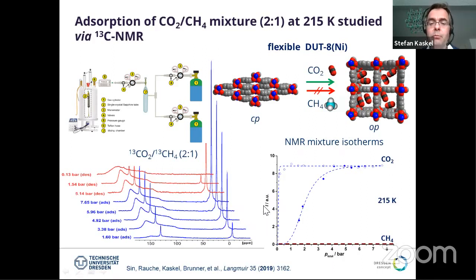So this is a fundamental proof of concept showing that in the switching MOFs, there's a very strong trend that if one species opens the pores, the other does not get access. It is still an open question why this is the case, but our interpretation is that there are restoring forces that still press on the CO2, basically. This is also the reason why we get this high anisotropy. And we think that this is the reason for this very high degree of selectivity.